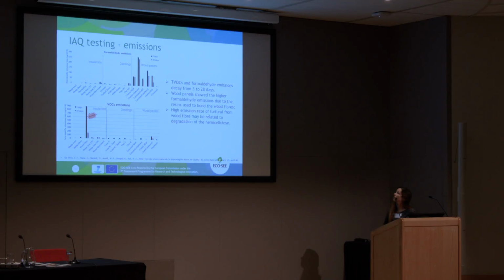In these graphs, you can see the emissions from the materials themselves, where I have only pure air going into the chambers. In terms of formaldehyde emissions, the materials that emitted more were obviously the wood panels, because the resins used to bind the wood fibers are based on urea formaldehyde resin. So that's where the formaldehyde is coming from. For VOCs, almost all materials emit very low quantities, apart from the wood fiber, which emitted furfural. This is related to the degradation of the hemicellulose.